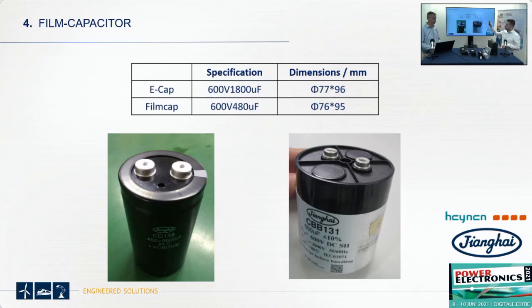So in fact, you have in the same dimensions and for the same voltage around 3 times higher capacitance for E-caps. That's not similar... No, it's not the similar product. There's a 600, and here we have 2000 volt. It's not the same thing. Here it's only a picture, but this is a 450 volt. But in fact, we compare 600 volt capacitors and a case size of phi 77 by 96.